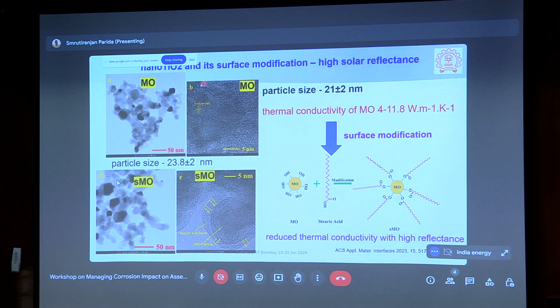a reflecting material that traditionally people have used, many solar reflecting materials, and we have chosen TiO2, nano TiO2. Because it's cheap and widely available, therefore we use it. So we have used a particle with a size of 21 nanometer average size.